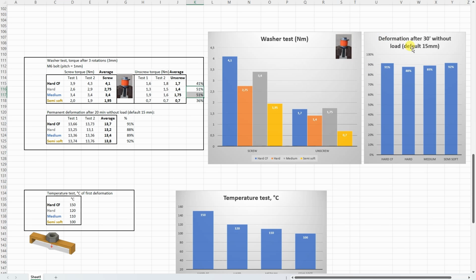And again, for me it is very important to see the deformation after 30 minutes without load. The default length is 15 millimeters, and unfortunately here more than 1 millimeter permanent deformation after 1 day when it was compressed to 12 millimeters.